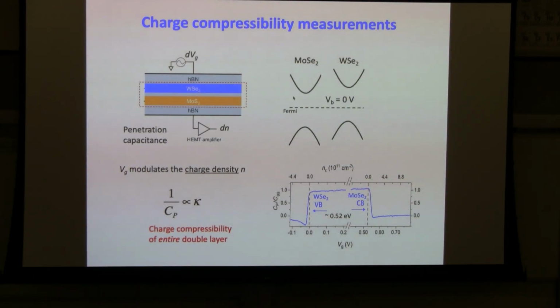There is no hBN between the two, right? There's hBN between the two. What's the thickness? It's about 2 nanometer. Yeah, 1 to 2 nanometer. What's confusing me is that your electric fields are all pointing up. Yeah. But the conduction that you'd have would be sideways. Yes, actually, you try to modulate the vertical electric field and then see whether the charge wants to move into the plane or not.